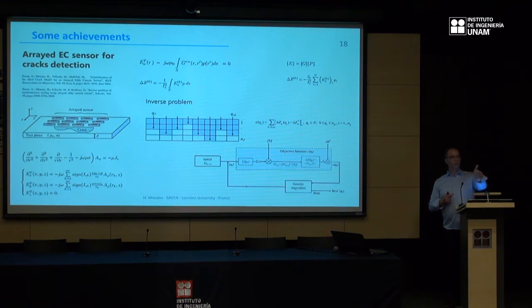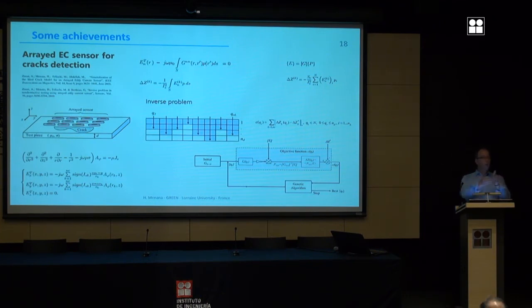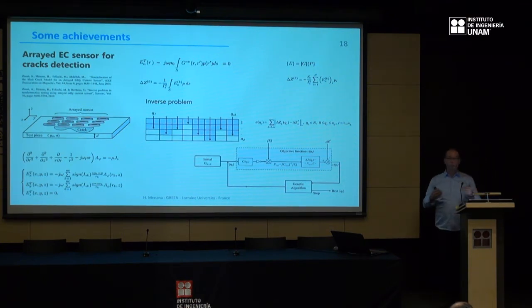Electric current cannot flow through the crack, so the normal component of the eddy current is nil on the crack, and this is achieved by this equation. We represent the crack by an electrical dipole P that cancels the normal component on the crack, instead of modeling the crack numerically. Because if you model the crack numerically, you have to mesh the crack, you have to put a very thin mesh in the crack.